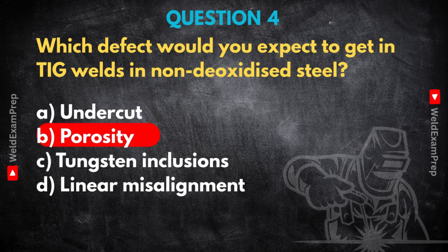Porosity again, but TIG has excellent shielding gas coverage, doesn't it? It does externally. The argon shield is very effective at keeping the atmosphere out. But the problem here comes from within the steel itself. Non-deoxidized steels have, well, higher levels of oxygen bound up in them, often as iron oxides. When you hit that steel with the intense heat of the TIG arc, that oxygen can react with the carbon that's also naturally present in the steel. This reaction forms carbon monoxide gas, CO.